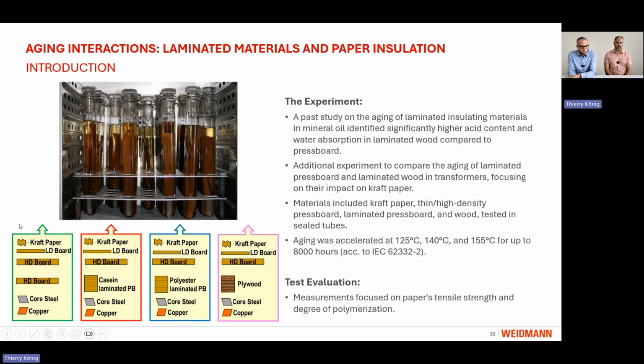For that, we used 4 types of test vessels, and in them we have multiple materials like kraft paper, low density board, high density board, and also copper and steel. The only difference between these 4 test vessels is that in one we have only high density board, so no laminated material. In one we have casein laminated material, one polyester, and in one laminated wood. We then applied aging to these test vessels at 125 degrees, 140 degrees and 155 degrees to see the impact on the paper insulation.